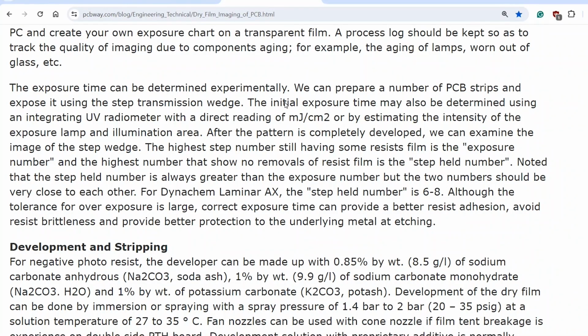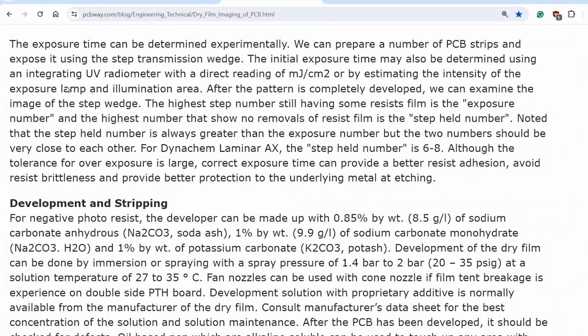We can prepare a number of PCB stripes and expose them using the step transmission wedge. This is how I did it. At the beginning, when I set up my exposure unit, I had no clue whether those were minutes, tenths of seconds, or a few seconds. I started with a maximum one-minute exposure and came down. 15 seconds is kind of optimum for my setup. 15 seconds is great, but I spent about 8 hours trying to find that optimum setup.